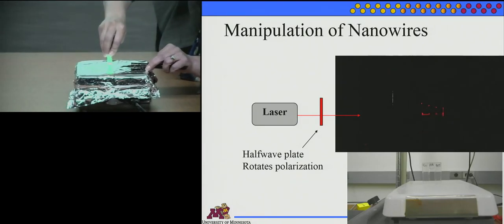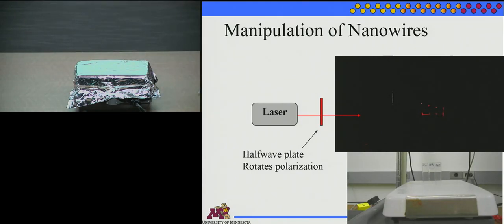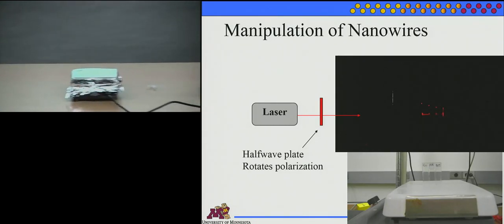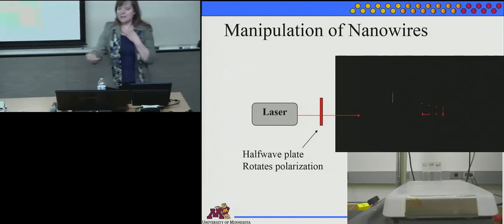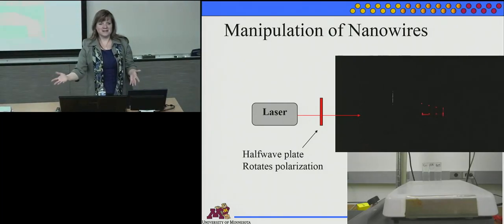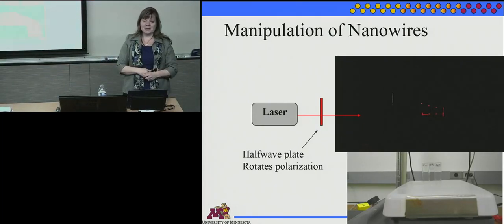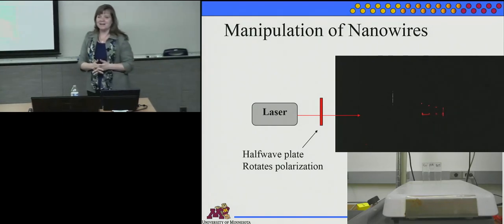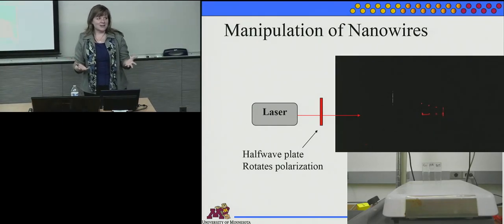Can you see a kind of a rotating motion? So that's the nanowires spinning around in there. And if I were to have an assistant from the audience, which I honestly don't think I have time for, I could speed it up and you'd watch it go faster and slow it down, and it would slow down. Because the nanowires are just responding to a magnetic field. It's so simple. We used to just do it as a trick for the program managers, so they'd give us more money. And then we realized we could use this too.